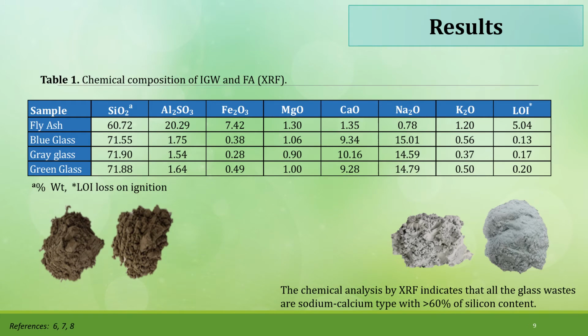It was observed that the fly ashes have as main oxides silicon, aluminum and iron oxides, and to a lesser extent calcium and magnesium oxide. According to the specifications of the ASTM C618 standard, the fly ash corresponds to a type F ash. Chemical analysis by XRF shows that glasses are made up of silicon oxide, sodium oxide, and calcium oxide to a greater extent, and iron oxide to a lesser extent. This indicated that the glass waste is the sodium-calcium type, and that its high silicon content makes it viable to be used as a source of silicon.